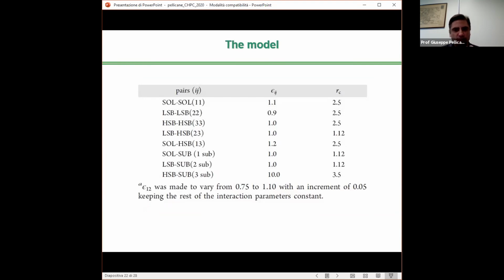So interactions between different types of non-bonded beads are calculated by using again the 12-6 Lennard-Jones potential. We are still using the bead-spring models for the polymers, and the list of parameters, so Lennard-Jones parameters for different cohesive and pairwise interactions, is shown in this table. The purpose of varying the Sol-LSB interaction parameter, the parameter epsilon 1,2, while keeping the other interaction parameters fixed, is to focus only on the effect of the quality of the solvent on the morphology of the simulated systems.